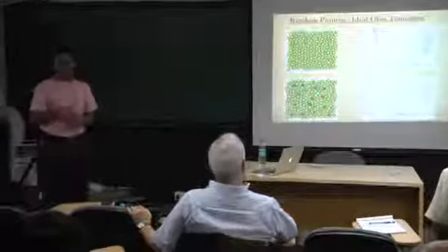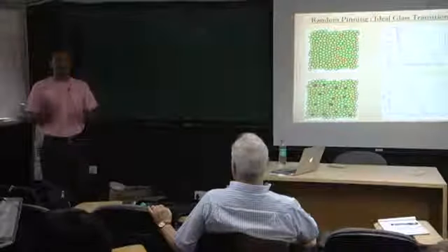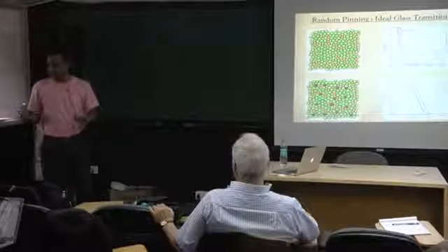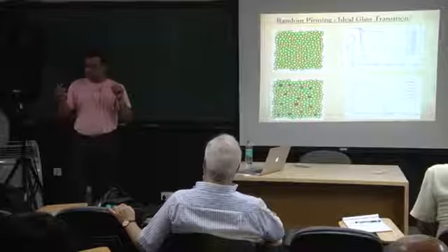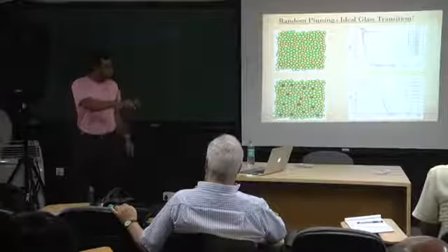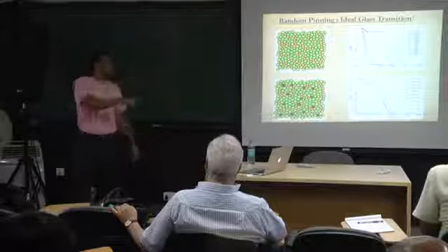If the glass exists, you can't reach it; before that you will run out of time and go into a non-equilibrium state. But here I am choosing the pinned particles from an equilibrium configuration, and by gradually increasing their number I am just increasing the corresponding time scale. I do not have to do equilibration again.